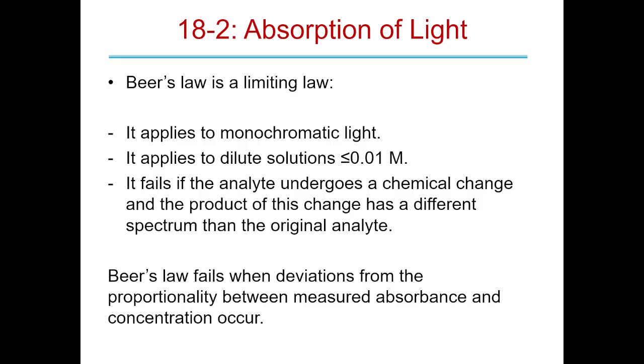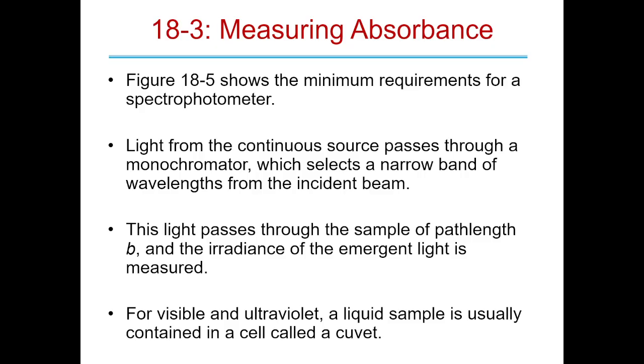Your background changes, doesn't it? Meaning your P0 changes. Okay. By the way, this is the most common mistake done in industry, if you're curious. The most common way to screw up in industry is that they will take a Beer's law, do all that work, backgrounds, Beer's law, everything, and they'll do it once a week or once a month, and it's too long of a duration. You can't use it for that long.